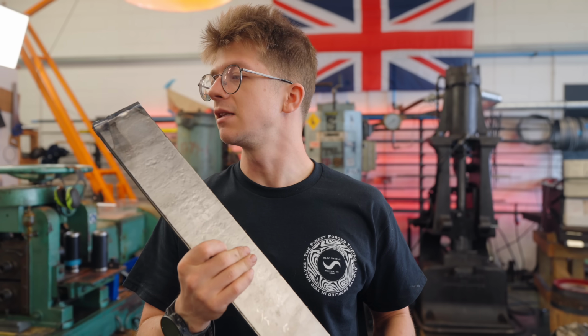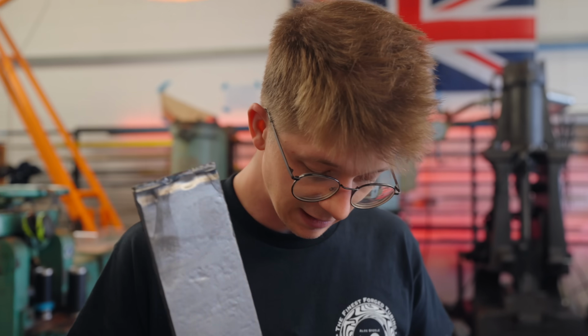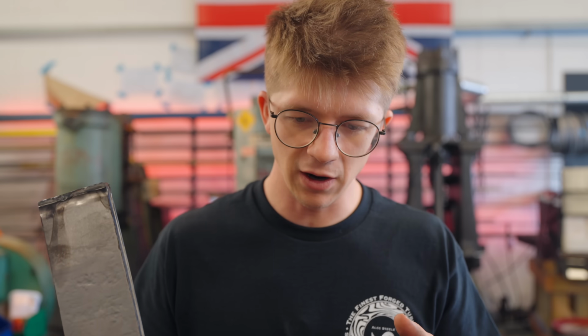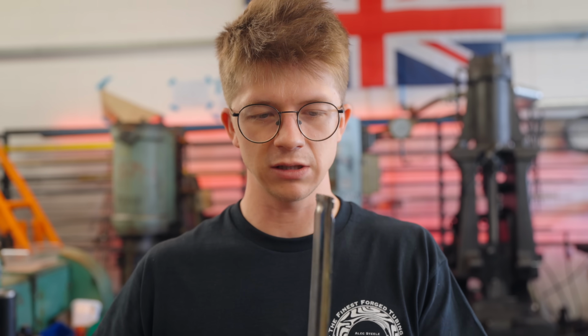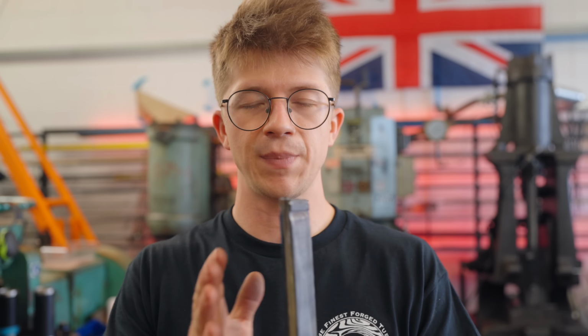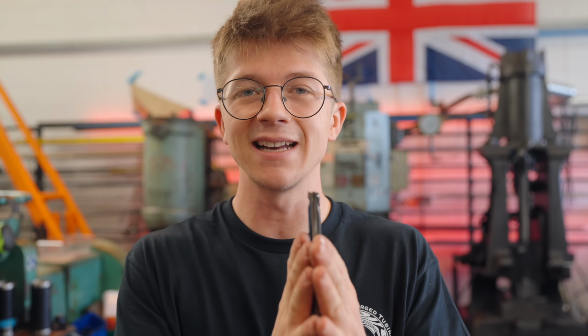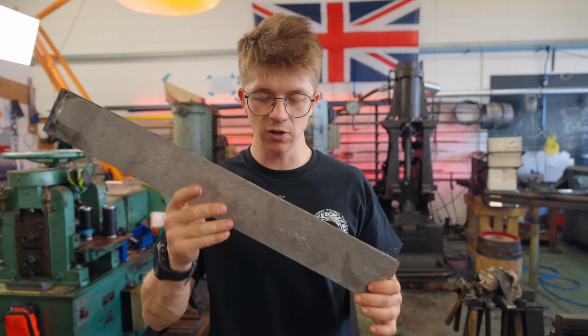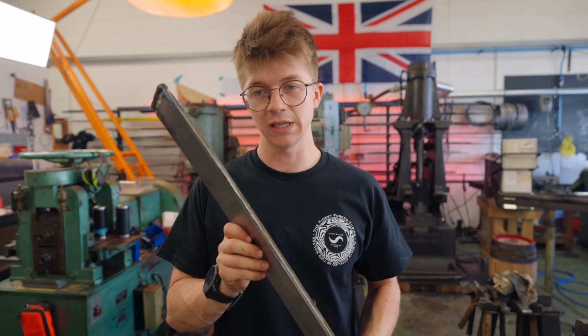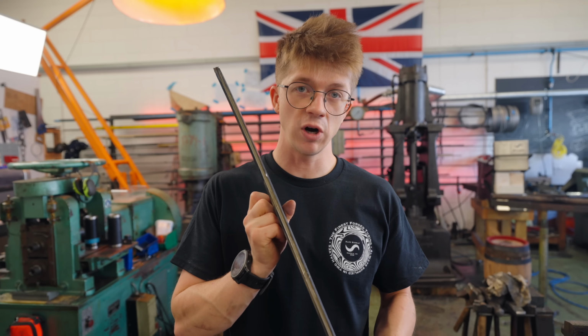Is that enough to get these bonds to stick? In industry, when diffusion bonding is done, they're often aiming for very little strain because it changes the cross-section of the part. But they're also doing the bonding over a significantly longer amount of time. They might be holding a part like this under pressure at temperature for like 2 hours. Here, I've got a few slaps of the hammer and that's all we've got. So we've got to use a lot more force, and more force means more strain, more squish.